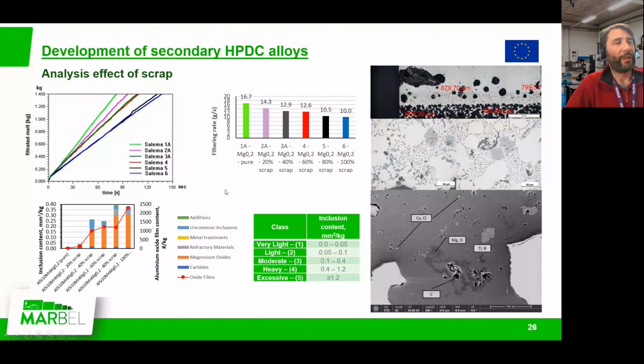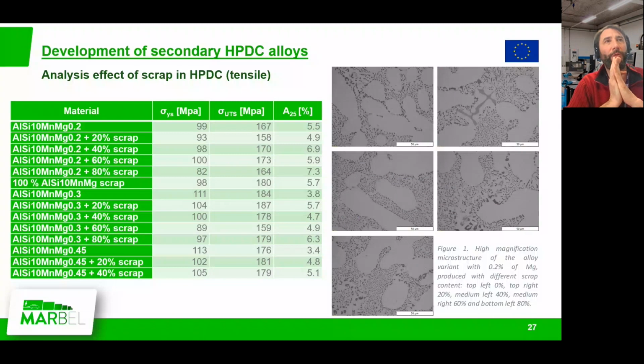So even if the chemical composition is the same or very similar, what we observe is that the presence of inclusions is higher, so a melt treatment is required in order to have the same quality of melt. So it cannot be directly used as scrap as an ingot. On the other hand, we also conducted mechanical characterization of these different alloy types, and we observe that the impact was very low on the mechanical properties. So the inclusions are present, they affect fluidity very much, but not as much the mechanical properties.